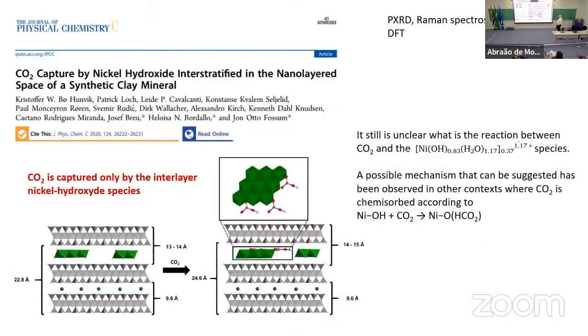What we further realized is that the CO2 is captured only in those interlayers that have nickel hydroxide. So the nickel hydroxide is the reason why we capture CO2. It's not the bare ion, it's the nickel hydroxide. Actually, how it captures CO2, we are not sure about yet. How it attaches to the nickel hydroxide is something we are working on.